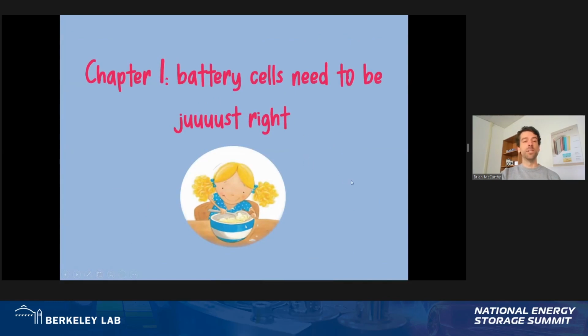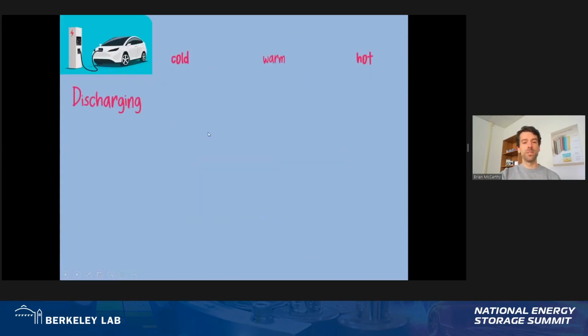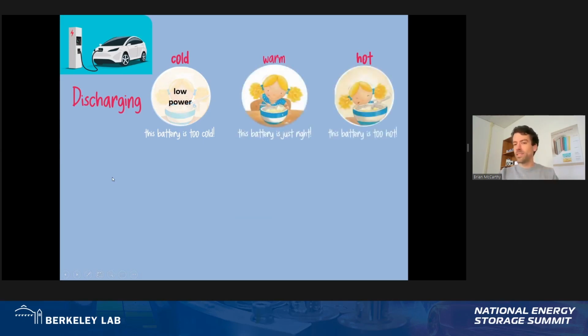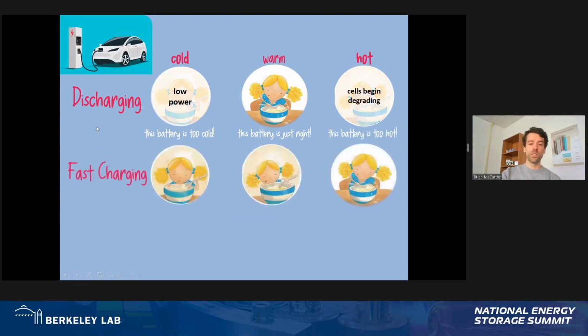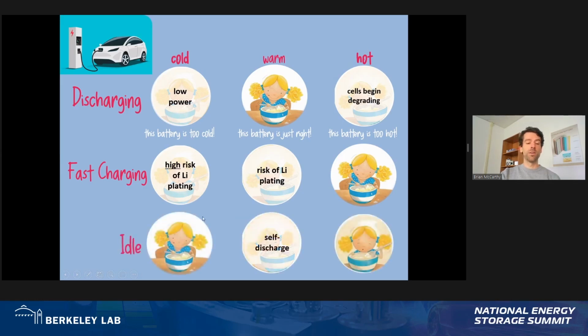Battery cells need to be just right. And by just right, I mean their temperature in an electric vehicle. When you're driving around, you don't want your battery pack to be too cold because then you have low power and low range. Rather, you want it to be warm, but not too hot because then you begin to degrade the cells. Now, if you want to fast charge those same batteries, you don't want them to be cold or warm because you risk lithium plating. Rather, you want them to be hot in order to have a safe fast charge. Finally, if your car is off, you really want those cells to be as cool as possible to limit self-discharge and calendar life loss. And this all points to the need for an active thermal management system.